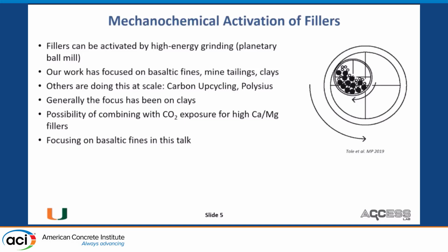The theory gets into complexity, and I'm not saying that you should mechanochemically activate all clays, but the statement I'll make is that if your clay is less than 30% kaolinitic content, there's probably a good amount of potential in mechanochemically activating it, both in terms of reactivity and workability improvement compared to the calcined clays.